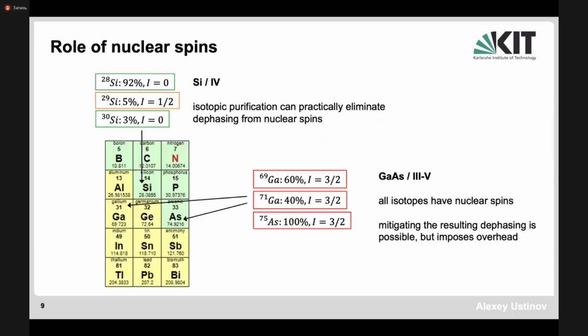And this is due to the spin states of the underlying structures. For gallium arsenide, the natural mixture of gallium and arsenic consists of isotopes which have nuclear spins. While mitigating the effects of these spins of the matrix crystal is possible, really it limits very significantly the spin coherence of the spin dots. You have some random noise of nuclear spins around, and these nuclear spins act as a noise source for the electron spins of the dots.